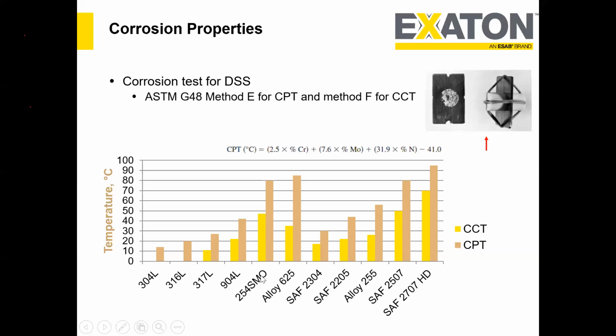So this is the alloy I want all of you to look at: Inconel 625, or alloy 625. It has a very good critical pitting temperature, around 85 degrees centigrade. But if you see here, the critical crevice temperature is only 33 or 35. So I have seen questions or inquiries asking, can we weld duplex with a 625?